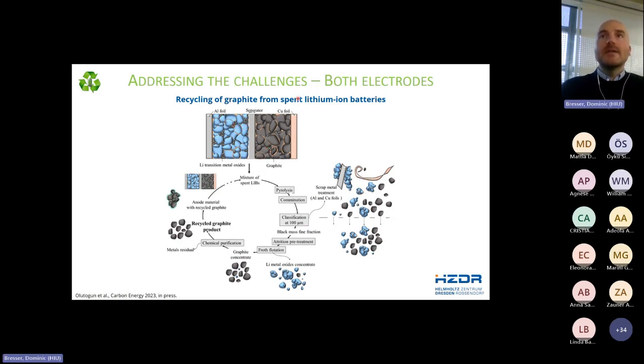So they use really spent lithium-ion batteries, right, commercial battery cells. And then they recover, or recycle, these in a multi-step process. And I will not go through all the details here. But what I would like to highlight is three things. So in the so-called black mass fine fraction, which contains all the active materials, almost 99% of the graphite particles end up in there. So we have a very limited loss of graphite at this stage.